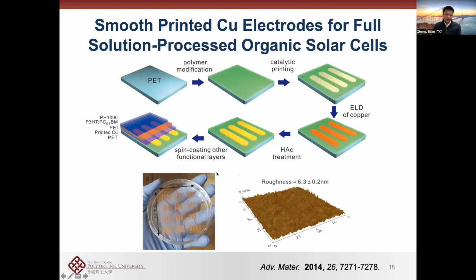Right, so the key thing here is we use this as the opaque electrode. Copper as opaque electrode for solar cells is rarely reported through a printing process, and the reason is that if you print a copper ink, for those who work with copper ink, they know copper ink is very difficult to print because of easy oxidation of copper and low conductivity. And if you use it for organic solar cell, you know that the roughness is a killing factor. It's very, very rough if you print particles.